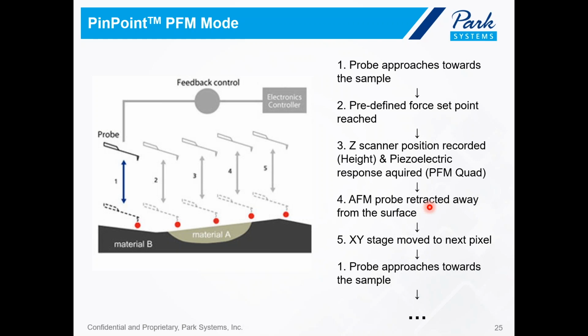And then the XY scanner will move to the next pixel. Then the probe will approach the sample again until a predefined set point is reached, followed by the Z-scanner position and piezoelectric response acquisition. Again, the AFM probe will retract away and the XY scanner will move to the next pixel. This entire process will repeat over and over until all the pixels within your image are scanned. And in the end, you will get a topography signal along with the piezoelectric response signal images.